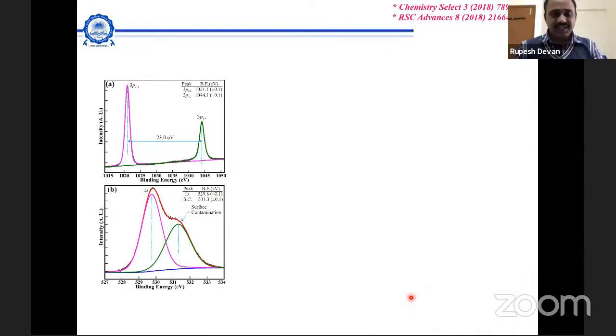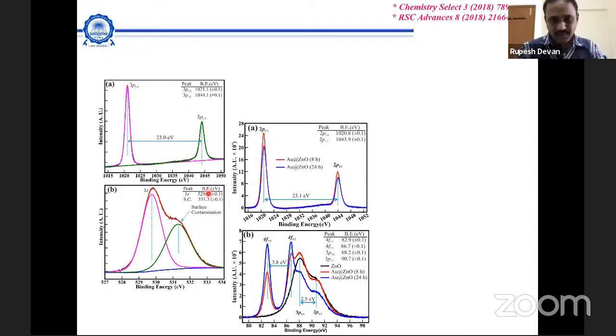The most important challenge, once you put this gold nanoparticle, is: does it tailor the properties of this zinc oxide? So first we check whether we have formed pure zinc oxide phase, then using XPS we confirm it. That is what we observe once you start coating the gold nanoparticles. What we have done is change the reaction time from 2 hours to 48 hours.